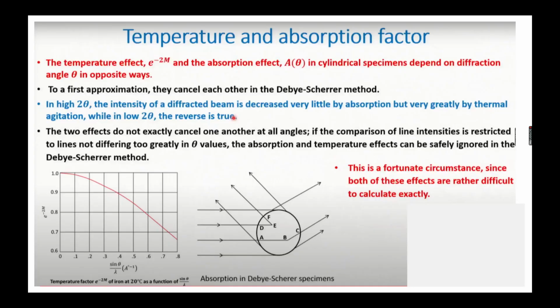No? Okay. So in this method, what can we ignore? Here it is saying that the temperature effect, e to the power minus 2M, and the absorption factor A(theta) in a cylindrical specimen depend on diffraction angle in opposite ways. So to a first approximation they can cancel each other. So in the Debye-Scherrer method, in the first approximation, the temperature effect and absorption effect cancel each other, and we can ignore both in this method.